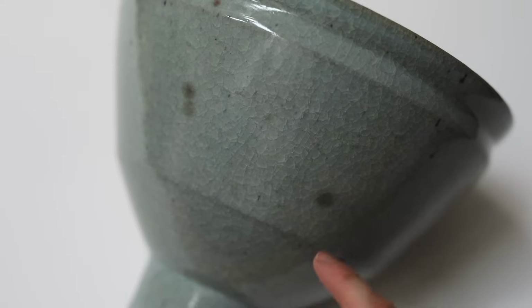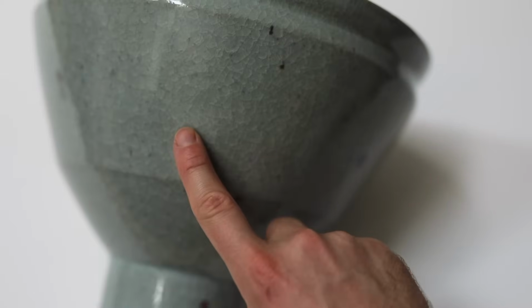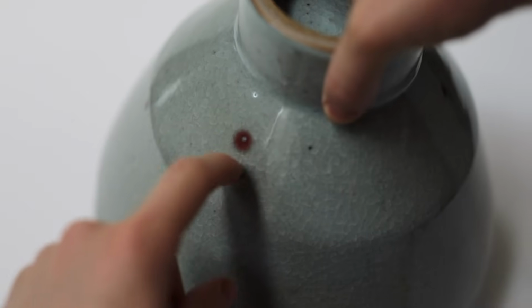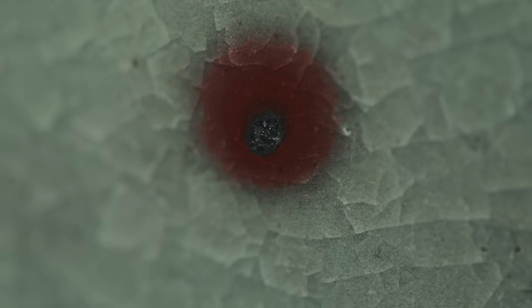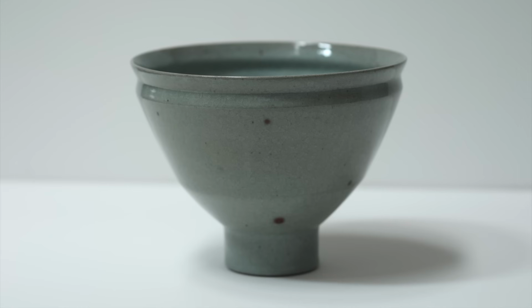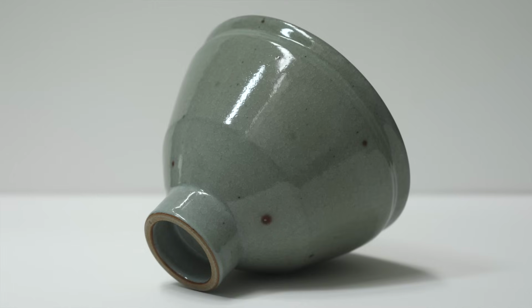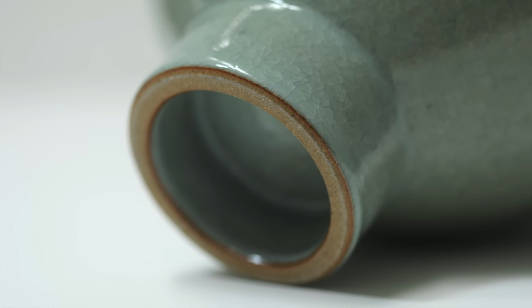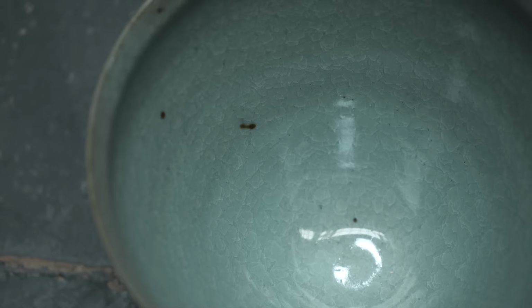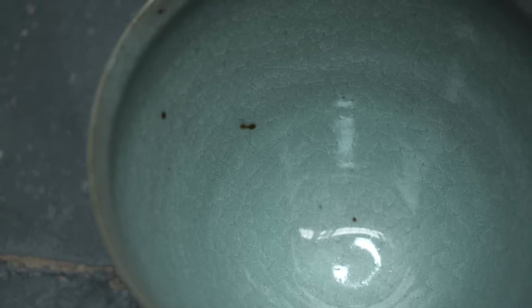Anyhow, let's have a look at the pale green feldspathic bowl first. Here are those grey flashes. They're quite interesting, in a way. You can see the piece of metal in the very centre that causes it, but they're nowhere near as dramatic as the red dots that are caused by copper within the bronze. I sort of look at these as beauty spots that cover the pot, breaking up what would otherwise be a very uniform surface. And they sort of help to draw your eye across the shape. You follow them from dot to dot, and it makes you want to look closely at the object.